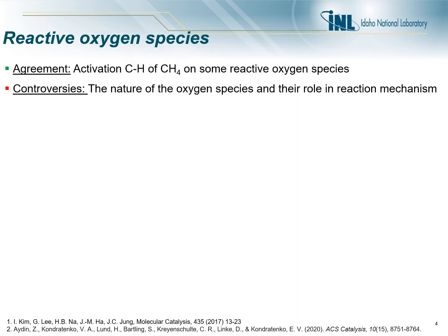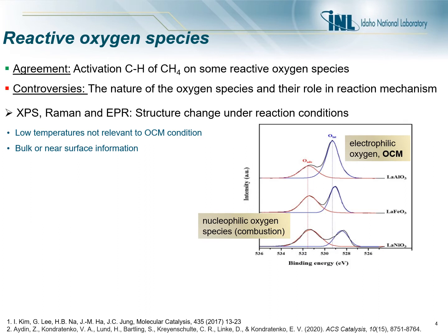There is agreement that CH4 activation occurs on some reactive oxygen species. However, the nature of the oxygen species and their role in the reaction mechanism is much controversial. There are many works on OCM catalyst structure characterization. For example, XPS is a powerful technique to investigate different oxygen species by looking at their binding energy. Then, depending on the binding energy, they can be assigned to selective or non-selective oxygen species.